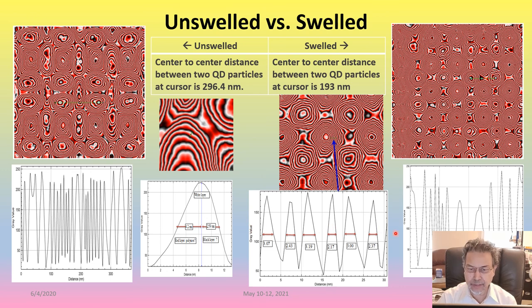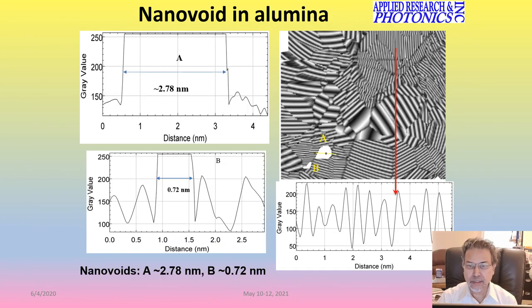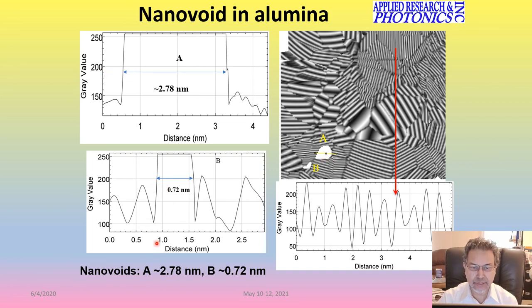Different layer thicknesses constitute the central quantum dot around which polymer and water layers are present. We can measure the thicknesses of each layer, their orientation, and organization. Here is another example of layer-by-layer analysis where grain size can also be measured from the profile. We can quantify the amorphous materials and different grain properties, and we found nano-voids within the alumina structure — we can also measure the nano-void sizes.